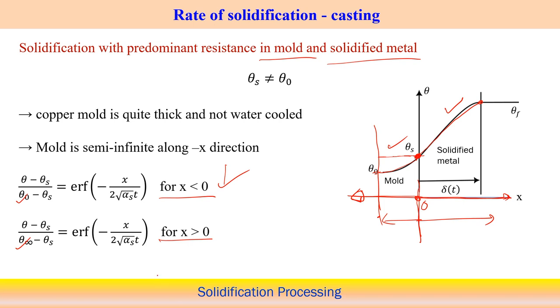So this is the one case, and the other case is (theta minus theta s) by (theta naught minus theta s) equals error function of minus x by 2 square root of alpha s into t. So here this is valid for x greater than 0. These two cases we can see are the temperature distribution, and it is basically represented in the form of an error function also, and we'll try to discuss these two equations of temperature distribution in these cases.